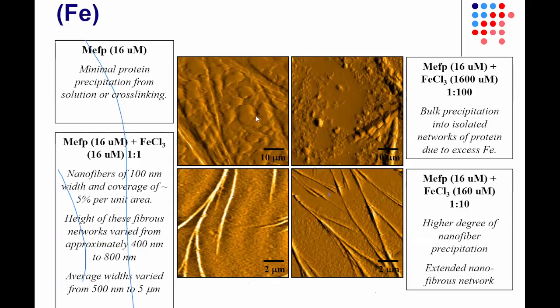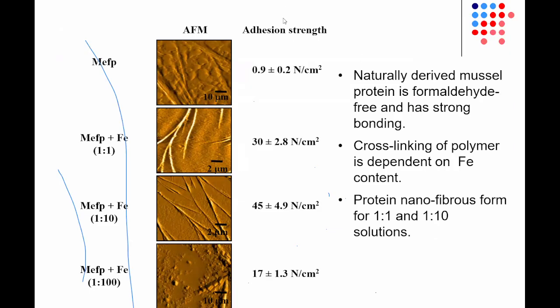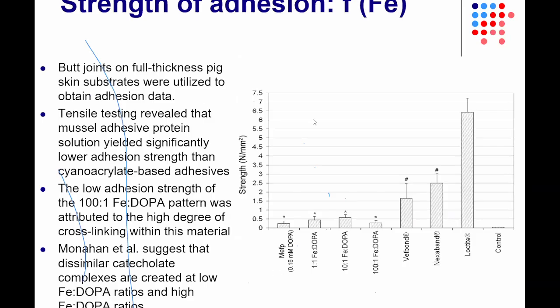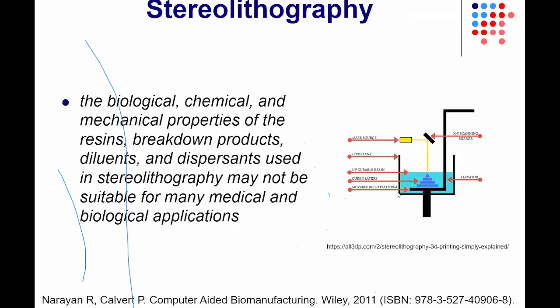because there's excess iron. And so you can see here as you go from 1 to 1, to 1 to 10, to 1 to 100 levels of protein to the iron chloride, you're increasing the cross-linking, and then you have these isolated networks when you have excess iron. You can see correspondingly an increase in adhesion strength up to the 1 to 10 ratio, and then a decrease in adhesion strength at a higher ratio. The strength of adhesion is also quite high for these systems, but not nearly as high as for conventional acrylate-based adhesives.